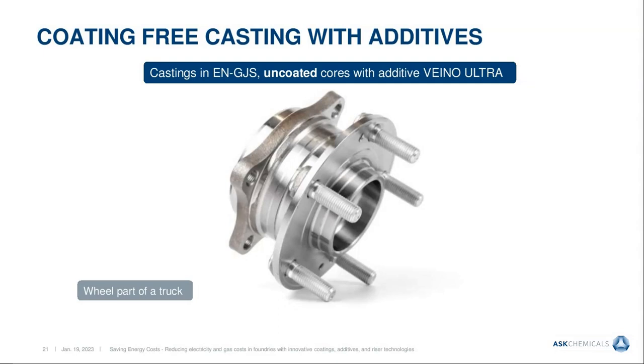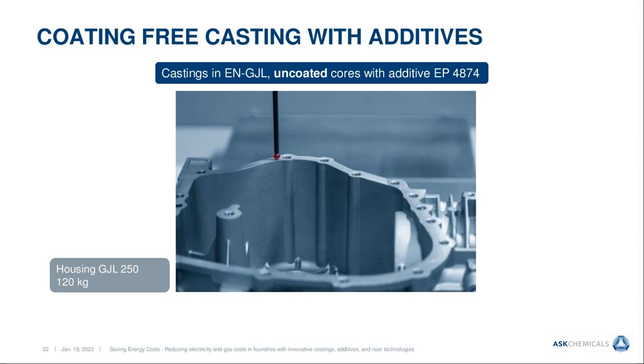This is a ductile iron casting, a wheel part of a truck, originally coated, and we could eliminate the coating process by implementing the additive Veino Ultra. And even on gray iron casting, we were capable to show that this concept works. Here's a housing of gray iron grade 250 with 120 kilogram weight, originally coated, and now the coating process has been eliminated by the additive EP4874.